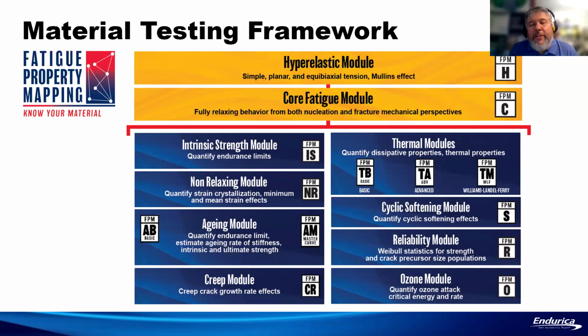I've colored the first 2 tests yellow because typically for any fatigue analysis, you're going to need to measure the hyperelastic module and the core module. The hyperelastic module is the stress strain curve for rubber in simple planar biaxial tension. It also characterizes the Mullins effect, which is a transient cyclic softening that rubber will exhibit. And that's required just to set up your finite element model in the first place.